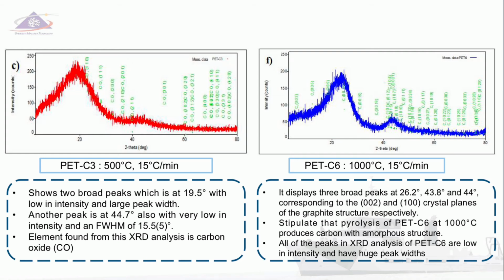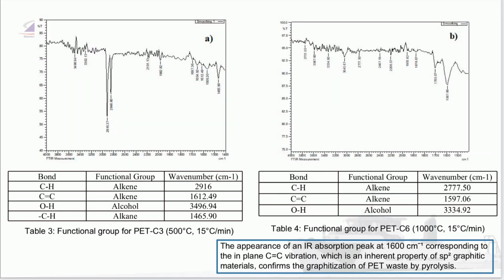PET-C3 only shows 2 broad peaks, which is at 19.5 degree with low intensity and large peak width, and an element of carbon dioxide was found, whereas PET-C6 displays 3 broad peaks at 26.2 degree, 43.8 degree, and 44 degree, corresponding to the 002 and 100 crystal planes of the graphite structure respectively, and stipulates that it produces carbon with amorphous structure. Next, the FTIR analysis of both PET-C3 and PET-C6 shows presence of functional groups such as alkene, alkane, and alcohol, which are comparable with the functional groups present in the commercial graphite.